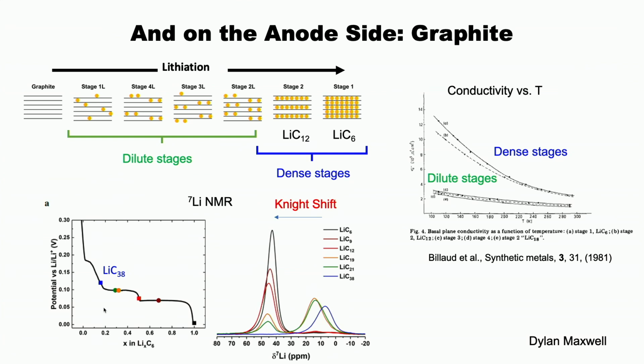And the thing about the dilute versus the denser stages, and this was something that Millie worked on, is you have very different conductivity. And so you go from the dilute stages that have very low conductivity to the dense ones that are very conducting. And you can see that by NMR. So this is the dilute stages, which have a very small shift. Once you form the dense ones, you have this large Knight shift, which is a measure of the density of states at the Fermi level as measured by the lithium.